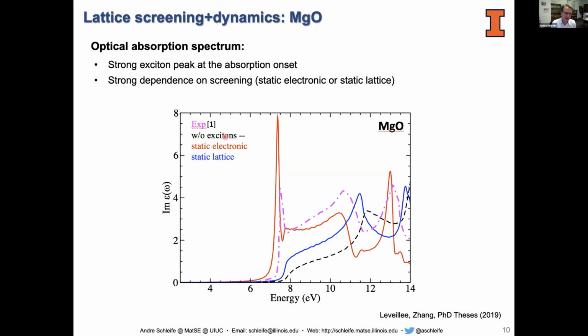What is more interesting is that if we screen the electron-electron interaction in the exciton statically electronically, we get the red curve. That's old data that we published a couple of years ago. If you screen with a complete static lattice contribution, you get this blue curve. If you use the static lattice screening, which we know is not correct, it overestimates the effect, but you can see the range between which you can tune this interaction, or between which we have to pick using the first principles implementation.